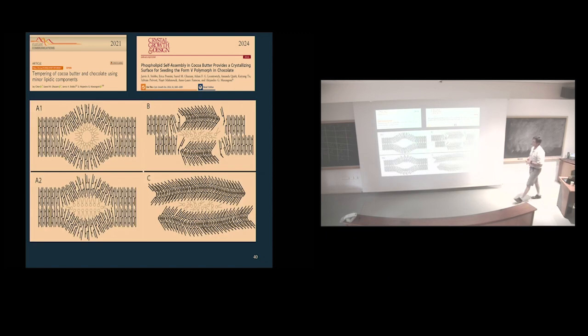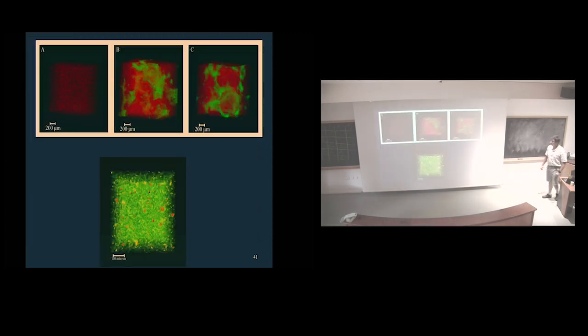And what Jarvis did in the end is suggest that you have the incorporation of the phospholipid. Look at these lamella, right? That's a bit of an exaggeration maybe, but it makes a good diagram. And as it gets crystallized and squeezed within it, the hypothesis we put forward is you create a slip plane between lamella, which allows the tilting of those chains in order to form the correct polymorphic form. So you start at certain temperatures with the existence of these, and then they get smooshed to death, and the material goes straight into the beta form. So that's the idea, you create slip planes that allow mobility of the chains in chocolate.